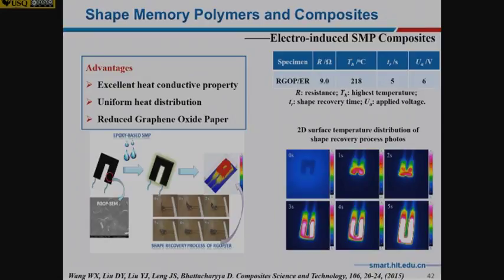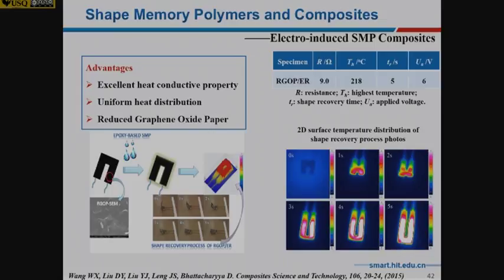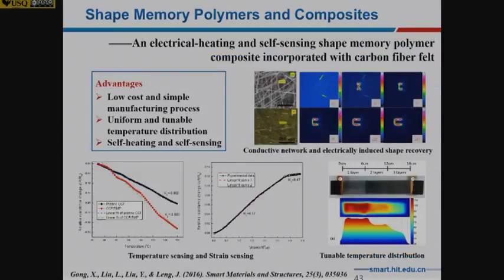So we also tried another conductive paper, which is a reduced graphene oxide paper. For this one, it's also very fast. The graphene has very good conductivity. You can see the temperature distribution, and when you apply some voltage, this can deploy very easily. And recently, we used the carbon fiber fabric. This one is also a heating element, also a sensing element. You can see the curve of this one, and also the temperature distributions.